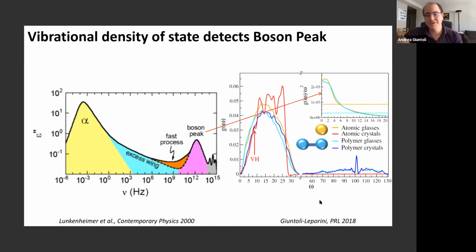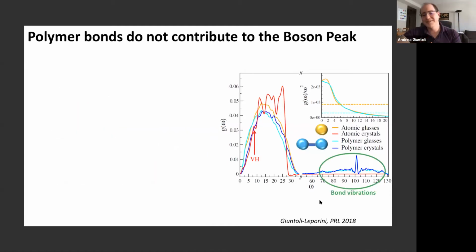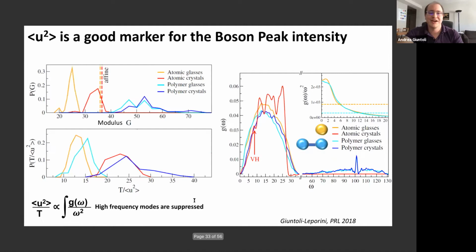And we found that this was due to the fact that polymer systems have bonds that vibrate very fast. So in this really high frequency range, they contribute to the elastic property of the system, but not to the boson peak. So in this case, we found that the modulus of the polymer system was higher than the modulus of the atomic system, so the modulus was not a good metric for the intensity of the boson peak, the Debye factor was.